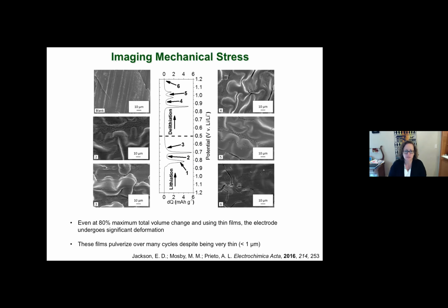So in these images, what I'm showing you in the middle is the differential capacity plot, so the lithiation and the delithiation. And then the numbers correspond to where we stopped, disassembled the cells, and then imaged the film. What you see when you start from just the blank film going to voltage number 2, then 3, then 4, you see the buckling of this film as it lithiates.